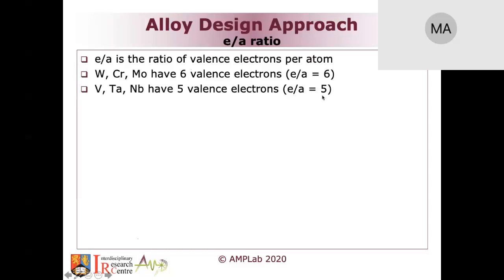So each alloy that you make has an overall E/A number. For instance, if you have an alloy which is 50% atomic tungsten and 50% atomic tantalum, 50% of this, 50% of that, that alloy has an E/A ratio of 5.5, which is the midpoint between the two.